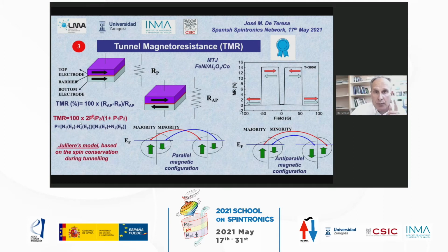In the model proposed by Julliere already in 75, he proposed that this tunnel magnetoresistance was proportional to the spin polarization at the Fermi level of the two ferromagnets. The spin polarization is the difference between the spin up and spin down subbands at the Fermi level.